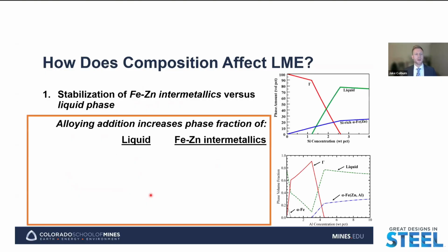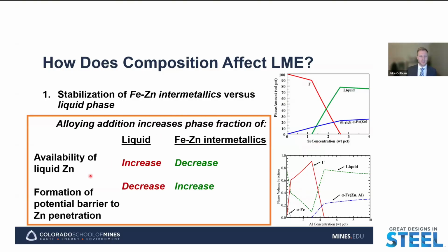So then going a little bit deeper in each of those 3 questions, again, with the first, the stabilization of iron-zinc intermetallics versus the liquid phase, we can go back to what we were looking at earlier of how aluminum and silicon concentration increase at the interface affects the equilibrium phase fraction of our phases of interest that are stable there. And we can then begin to say, with that alloying addition, if we're stabilized in the liquid phase, we're then going to increase the availability of liquid zinc while decreasing the potential for forming this barrier to zinc penetration.